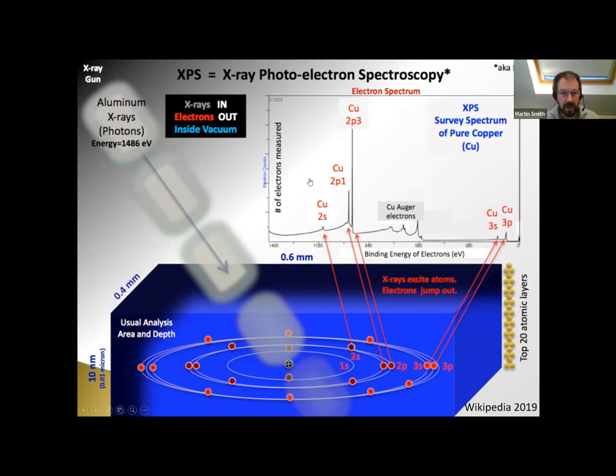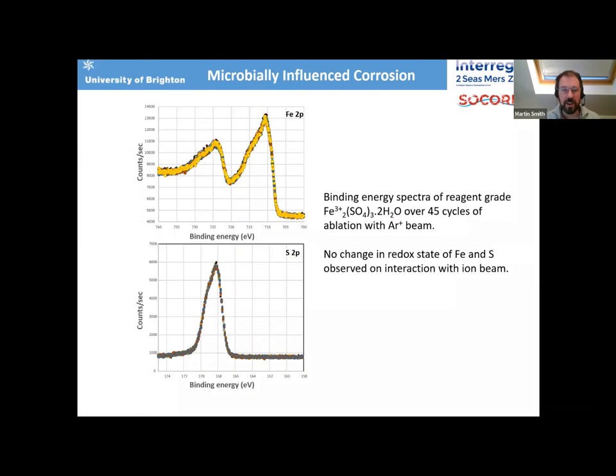We couple this with an argon ablation beam, and we can sputter into the corrosion sample surface, and look at changes through the structure of those blisters. There are issues with that, because firing an argon plus beam at the sample surface can induce its own redox chemistry. But just to demonstrate what's going on here, these are binding energy spectra of iron and sulfur 2p electrons, ablated over 45 cycles with the argon plus beam, and we ablated into laboratory reagent grade hydrated iron sulfate samples here, just to demonstrate we're not seeing oxidation or reduction of sulfur during the ablation process.